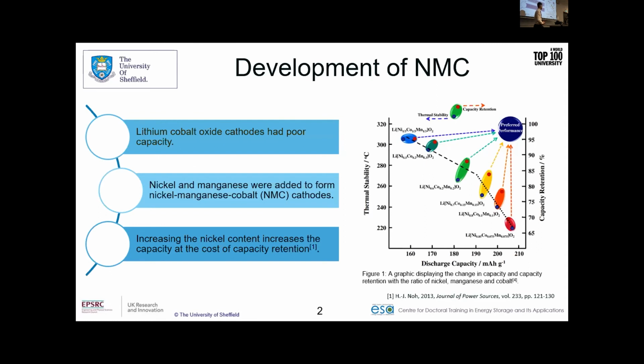So alternative chemistries were looked at. And one of the main candidates to sort of take over from these LCO materials were nickel, manganese, cobalt cathodes. I'll use NMC as the abbreviation from now on, just for simplicity. And these provided an increased practical capacity, so we could get high capacities, as well as maintaining some of the stabilities and some of the nice safe properties that we were looking for in the cathode materials. And it was found that although we started with this material here called NMC 111, where each nickel, cobalt, and manganese had a 1-to-1-to-1 ratio, we could increase the nickel capacity. So it was nickel 5, cobalt 2, manganese 3, up to what we were more looking for nowadays, which is nickel 8, cobalt 1, manganese 1, and above that.